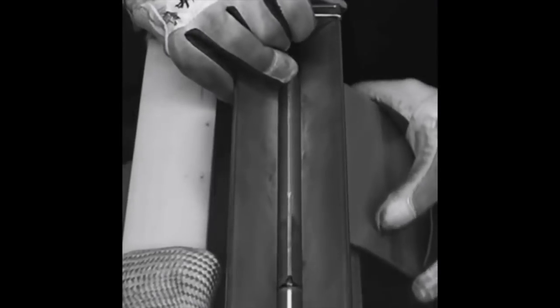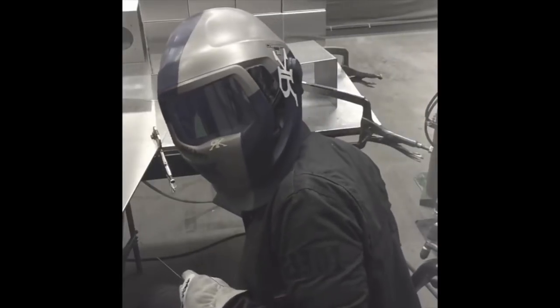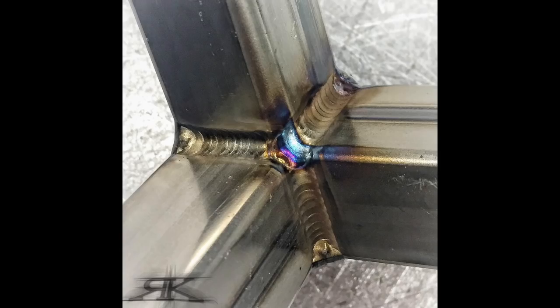So I made this little palm sled device. It's basically just a 90-degree angle, and it has some nylon plates on it, and the plates are mounted to this little piece of angle, and it has a little stem that you can hold on to. It allows you to put that on the edge of your table, the edge of a piece of angle iron, even on a piece of round tube, and you can set your hand on that, and if you're welding in a straight line, you can glide your hand on this with minimal friction and keep a really steady and consistent motion with your torch and keep that constant momentum, help stabilize and create a nice looking weld. Do you end up still using it very often?